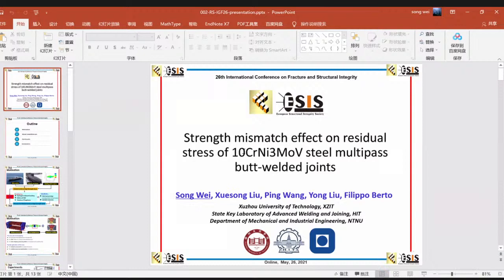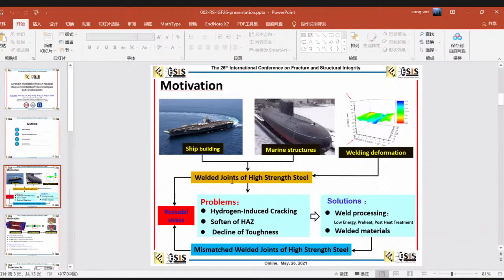The undermatched materials affect the maximum residual stress value. As we can see, due to the SSPT effect for the even matched weldment, the residual stress is lower than the undermatched weldment. So I think the undermatched material does affect the maximum magnitude of the residual stress. Will it increase or decrease residual stress? Yes, a little bit. It's near the yield stress of the undermatched material. So it will increase. Okay, thank you.